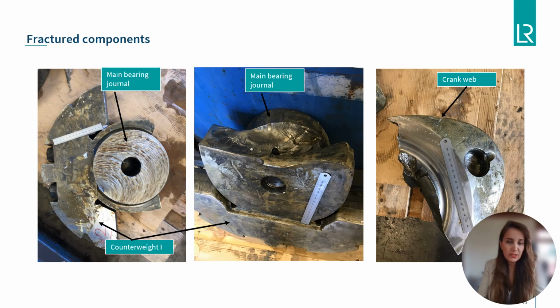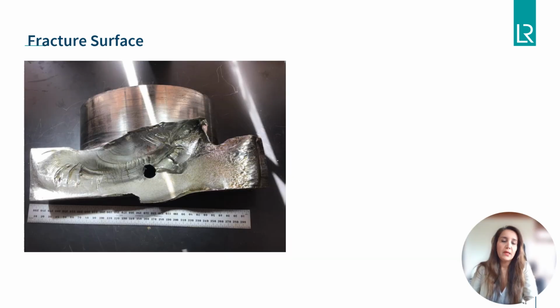In these images, you can see the location of the failure in relation to the main bearing journal and crank web. The image in the middle is the same component as on the left, only taken from another angle to show the failure location and fracture surface more clearly. As I mentioned earlier, all components were cleaned to allow further investigation. Now you can see the fracture surface a lot better in these images.